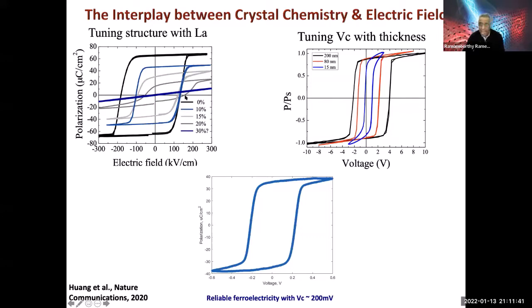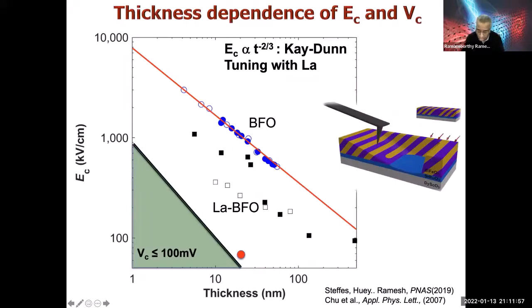Okay, very quickly, this is our state of the art. By tuning the thickness and the chemical composition, we know we can get to bismuth ferrite with 200 millivolt coercive voltage. Very good hysteresis loops. Of course, these are epitaxial samples, but we know we can get good quality material. Now, a few years ago with Brian Huey, we looked at the thickness scaling. Just a quick aside: you can now use the atomic force microscope not only to look at the coercive voltage on a local region, but you can also atomically shave it. That's what he did. He used the AFM tip to shave layers and then measured the coercive field as a function of thickness. That's shown here, and this is the so-called Kay-Dunn law.